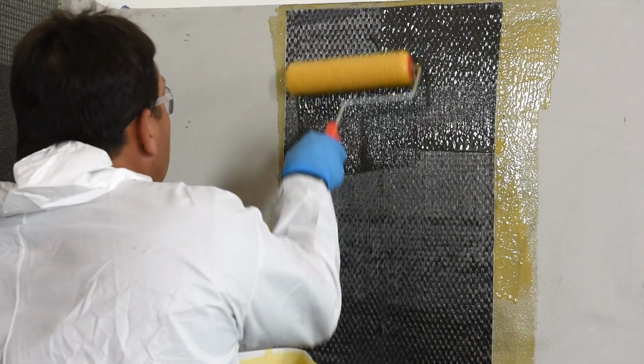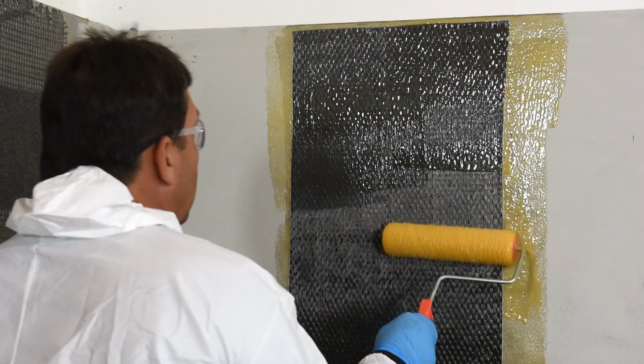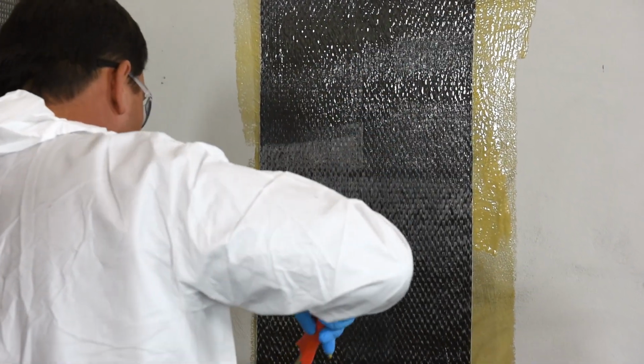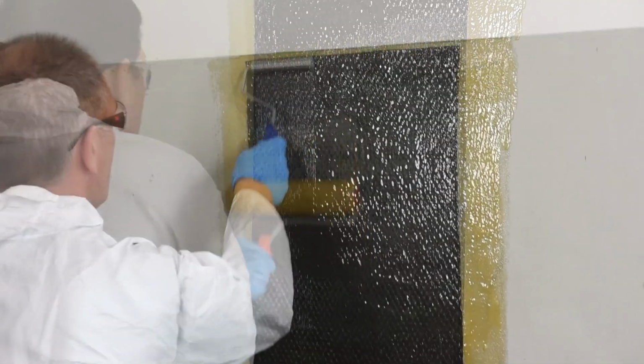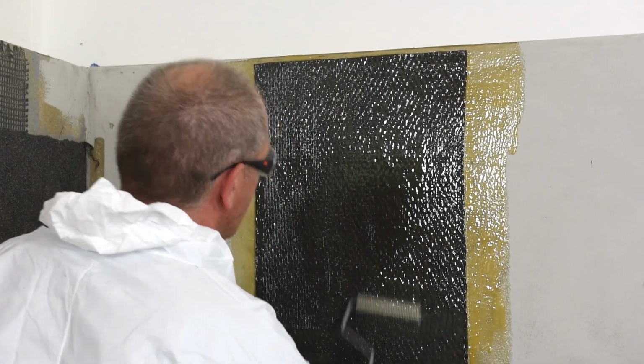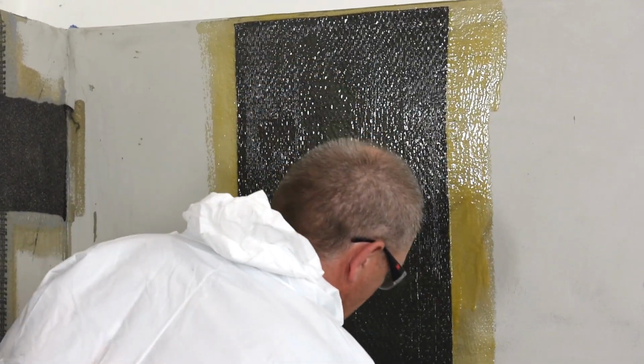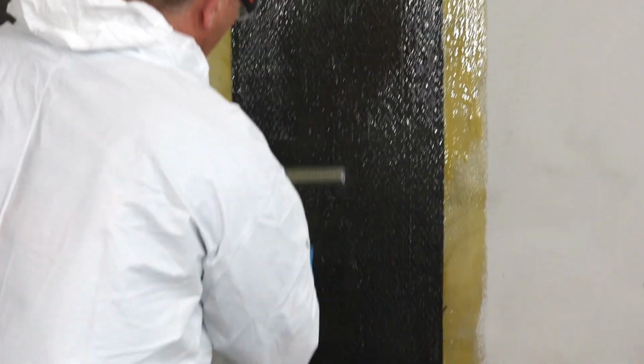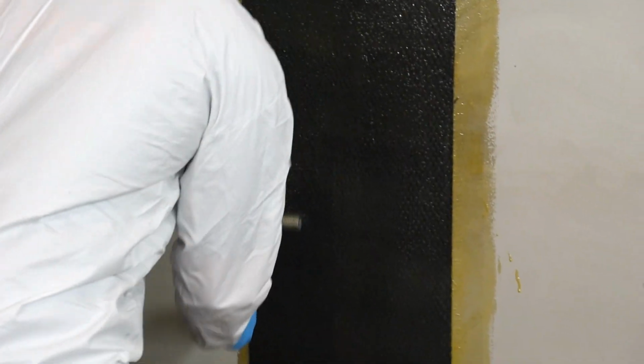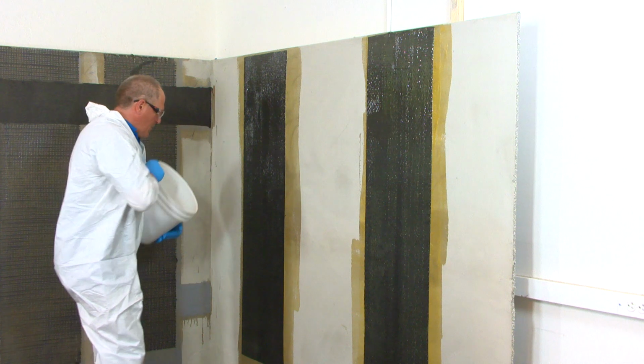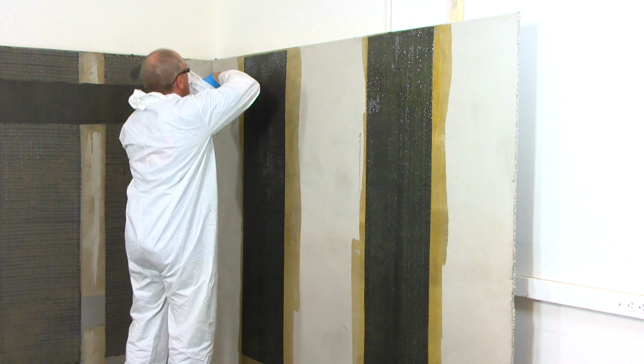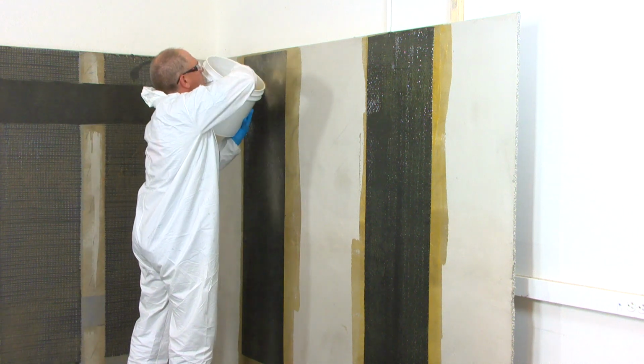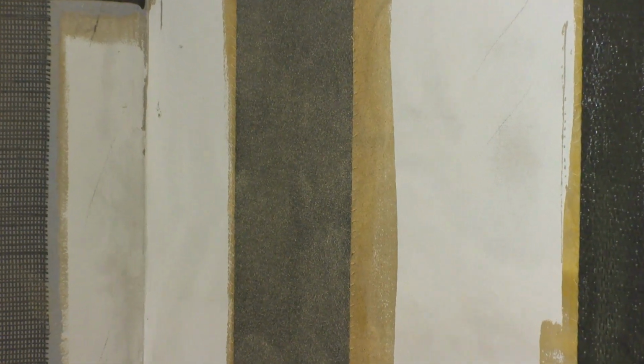After applying the MapeWrap Uniax fabric and removing any creases, apply a second coat of MapeWrap 31 by brush or roller. Work the fabric with a ribbed roller to help the resin saturate the fabric and to remove any air voids that may be trapped behind the fiber. While the MapeWrap 31 is still wet, the installer will sand broadcast oven-dried silica sand that is 20 to 30 mesh in size. This sand broadcast provides a mechanical bond for other finishing materials if needed.